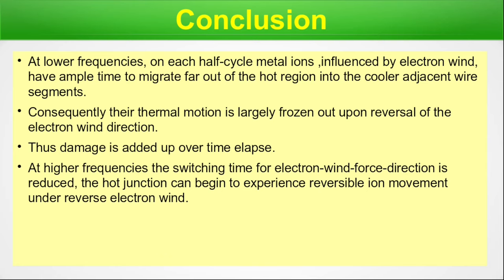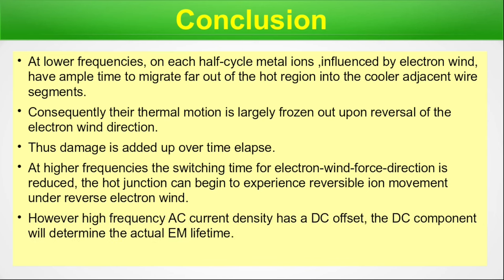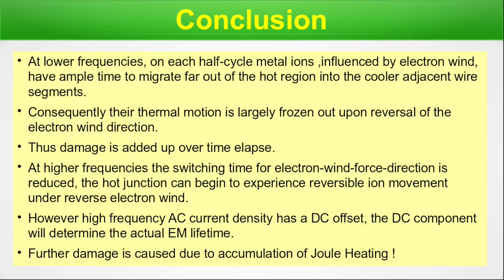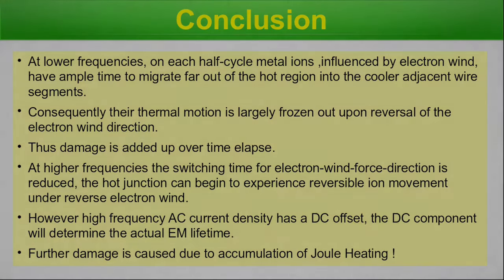At higher frequencies, the switching time for the electron wind force direction is reduced. The hot junction can begin to experience reversible ion movement under reverse electron wind. However, high frequency AC current density has a DC offset, the DC component will determine the actual EM lifetime. Further damage is caused due to the accumulation of the Joule heating. We are done with this particular slide, so let's move on.